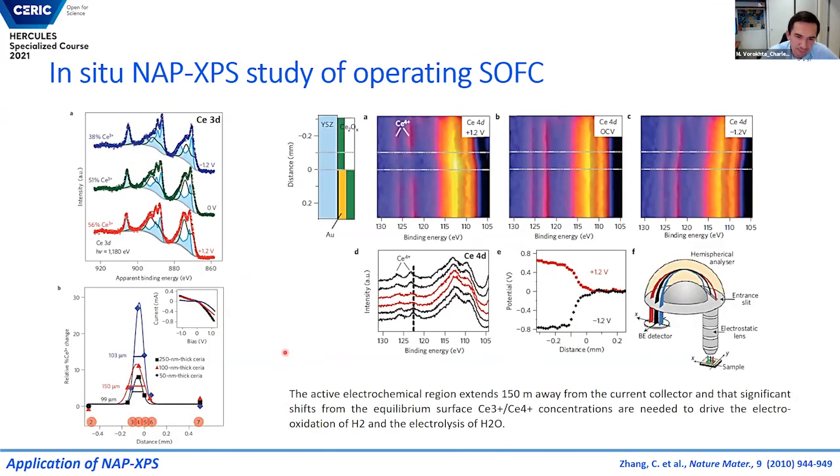And then here is some 2D map which shows people were scanning at different distances. It starts from some far place of the interface where YSZ is interacting with ceria, and where the ceria is on this gold electrode. You see that in this region, which is close here at some distance, you have no cerium 4+, so the reaction takes place exactly here.